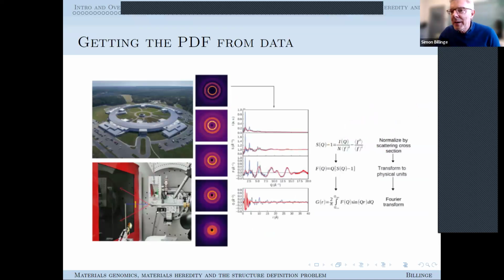These are the kind of experiments that we do to get it. So we have this $1 billion synchrotron, and we put our little bit of powder right here at the end of this tube, and this very intense X-ray comes down the tube, hits the sample, and goes into the detector. This is a one-dimensional PDF. We get an isotropic signal coming out, and we integrate it, and we do corrections, and then we get our PDF.